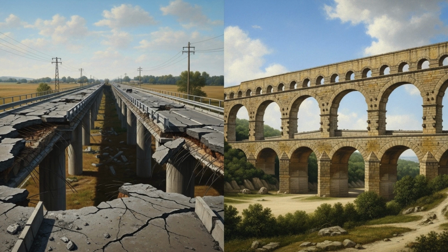And they're brilliant. The Romans used hot mixing, adding quicklime, calcium oxide, directly to the mix instead of pre-slaking it into lime putty. This created two things. 1. Extreme heat during mixing, up to 200 degrees Celsius, which changed the chemistry and allowed different minerals to form. Point 2. Reactive lime clasts scattered throughout the concrete, small reservoirs of calcium hydroxide.